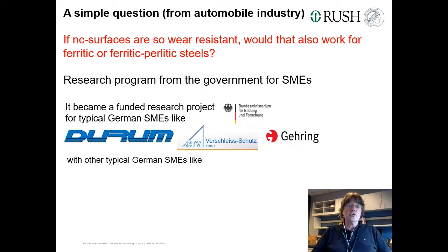Because Chrissy asked me to say something about coatings we did, especially sprayed coatings, I added some other things at the verge between fundamental and applied tribology, which is covered by the PhD thesis of Marijke Hahn. So the question is, if the nanocrystalline surface in your tribological system is so good, why don't we just generate a nanocrystalline coating on the surface which lasts forever? And would that also work in ferritic or ferritic-pearlitic steels? Because again, they are even cheaper than the martensitic stuff.